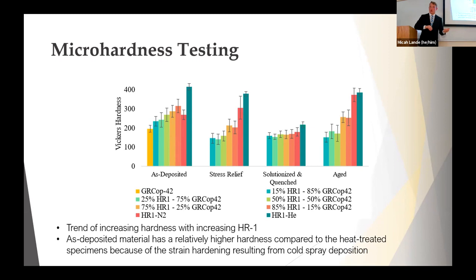And the same thing happens when we go in for solutionizing and quenching. All that is again brought down, but what's interesting here is that if you match up the higher copper content deposits, these actually don't change all that much, but as you start increasing the HR1 content, those come down quite a lot, mainly because HR1, unlike GRCop-42, is not dispersion strengthened, so it's more susceptible to heat treatment. And then after the aging process, we see that ramp back up of some of them going back to similar hardness levels as before, but again, this is just one of many properties.